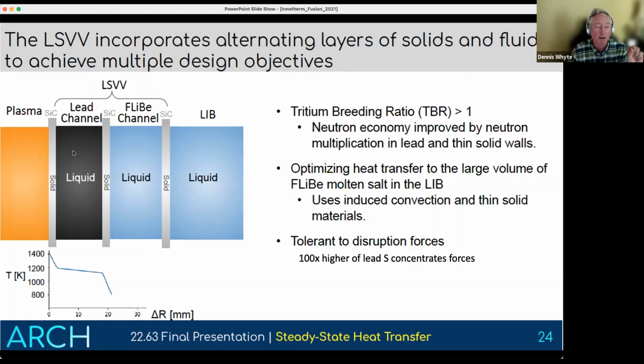And what we have for interleaved liquid layers is a channel in here of liquid lead, not the salt, but liquid lead. And then on the outside, we'd have forced convective flow of the salt, which is the flibe. And then over on the far right is the global heat sink, the large blanket. This gives you an indication of the challenges of this: down below you see the temperature profile in Kelvin, because these are the heat fluxes which are in place. Silicon carbide doesn't have great thermal conductivity, so you can see that even though this is only a few millimeters thick, there's like a 200 Kelvin drop across this thing. But then across the liquid, it's that, then across the next solid.